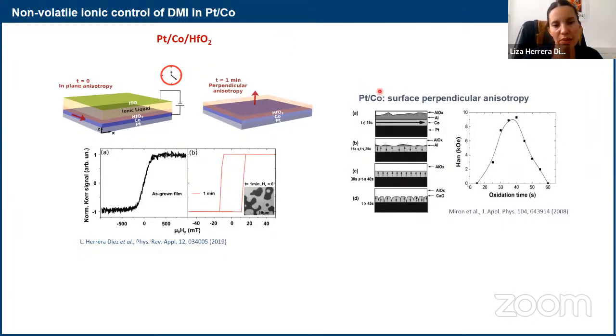So I told you already about oxidation, but it's nice to see that studies were done much before any of this magneto-ionics was being done. And then one of the groups in Grenoble was showing that for platinum, cobalt, alumina, they could see how the perpendicular anisotropy would depend on the degree of oxidation at the cobalt oxide interface. So this basically shows that there is a window of optimum oxidation that gives the highest values of PMA. But if there is too little oxygen, or if there's too much oxygen, then PMA will be lost.